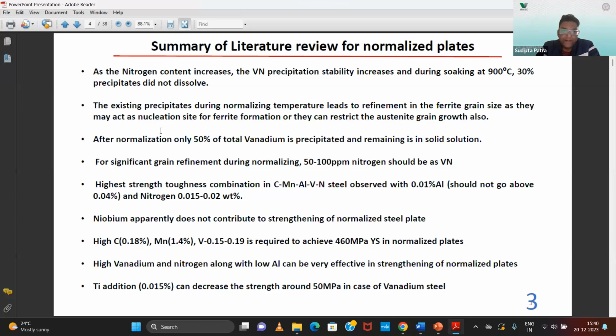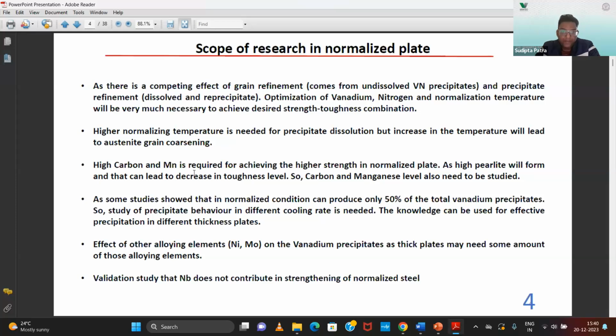So here the literature review and scope is that there is a lot of literature on these vanadium alloyed steels and their precipitation strengthening, but the unique aspect is in the normalized condition, when we are trying to austenitize at 900 degrees centigrade temperature. There you know that some precipitate will dissolve and some precipitate will remain undissolved. We always want the dissolved precipitate, so the vanadium will be in the solid solution, and then when we cool it, we will get the fresh and very fine precipitate, so that we will get very high precipitation strengthening. But at the same time, the undissolved precipitate will pin down the austenite grain boundary, and they will not allow the austenite to grow. So we will get very fine grain.